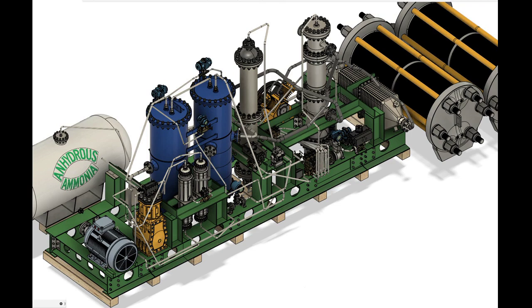Rather, a hydraulic piston beneath a layer of ionic liquid above it forces the entire assembly to move upward. In this case, the ionic liquid itself is not a working fluid per se, but merely a receptacle for the hydraulic fluid. It is akin to a separation medium to prevent contamination of the product gases, while also doubling up as a lubricant and coolant, both reducing friction and providing near isothermal operation, through the absorption of the thermal energy generated from the compressed gases, truly a versatile molecule. The ionic liquid can then be recirculated and cooled to maintain a constant temperature.